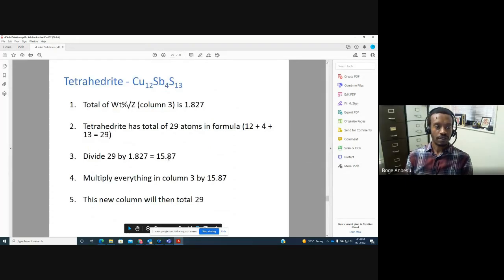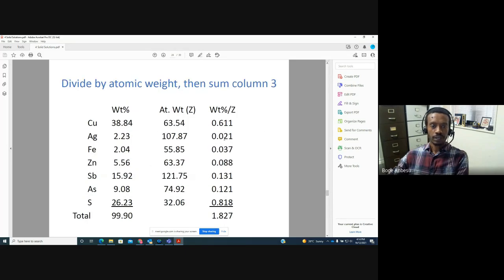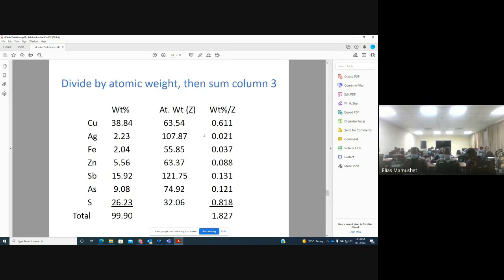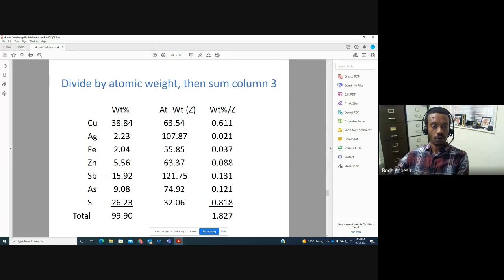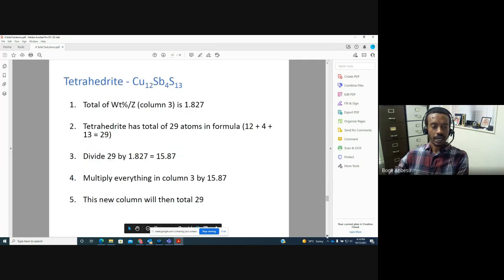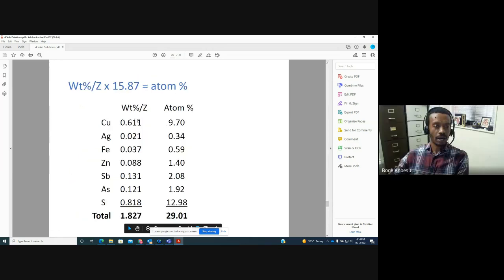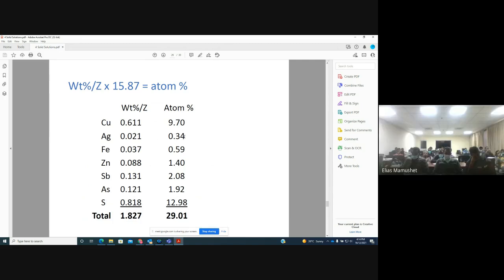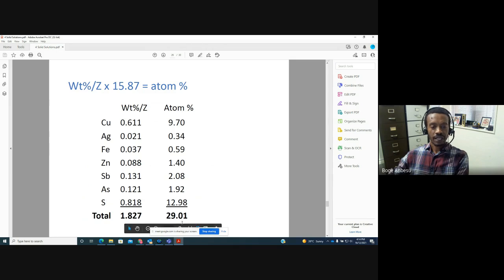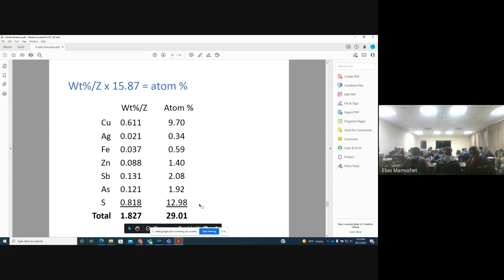Okay, so 15.87 multiplied by each of these in the fourth column, and I will get the total adding up to 29. So if I multiply everything by 15.87, I'll get about 9.7 copper, about 0.34 silver. Everything adds up to about 29. So it tells me that actually there is not much other impurity. It's still tetrahedrite.